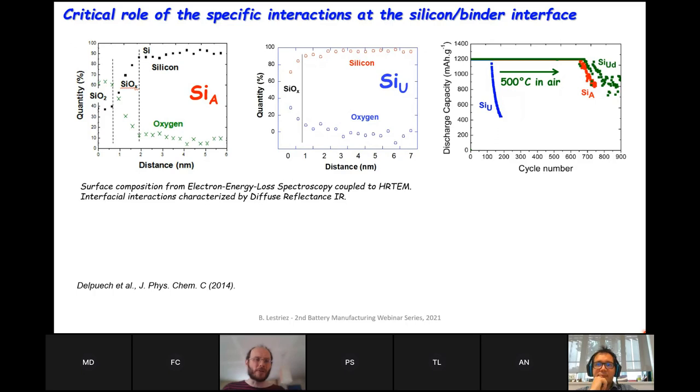You see that this silicon A is covered by a very well-defined silica layer, which is not the case of silicon U in blue in the middle, where there is only a suboxide with a low amount of oxygen at the surface. But if you oxidize this silicon U in air at high temperature, it's the green curve on the right, you see that you recover a very nice cyclability. So next, that shows that